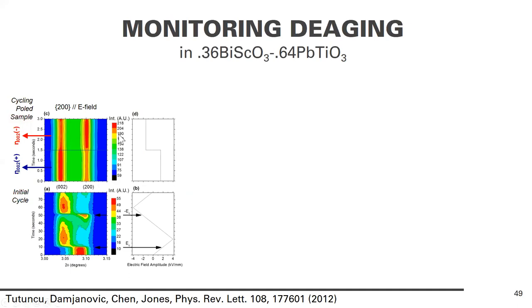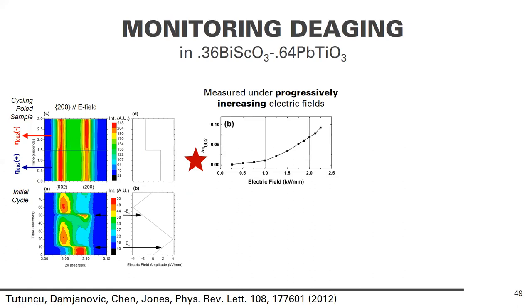negative directions. Now, we did this experiment under progressively increasing electric fields, similar to the upward trend on the data on the previous slide. And you can plot the difference between these two as an indicator of the extent of domain wall motion in the poled state. So this is delta eta 002 as a function of electric field amplitude.